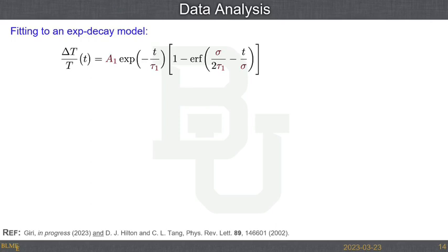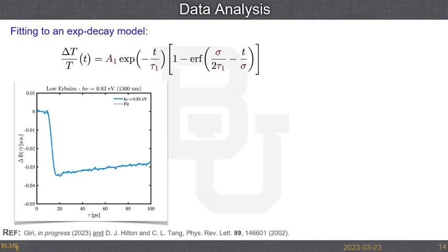Why is this busy? There we go. So what am I looking at here? I come through with my optical pulse. I put a whole bunch of carriers inside the material. For this period of time, my pulse is coming through the system, and I'm populating that upper level, whether it's 2 or 3 depending upon the wavelength. And so I'm seeing a drop in the transmission of the terahertz pulse as a result. I've got all of these carriers in there, and so instead of the sample allowing the terahertz pulse to propagate through, it's actually reflecting it. So I'm turning this material into a very good mirror in basically a picosecond time frame.